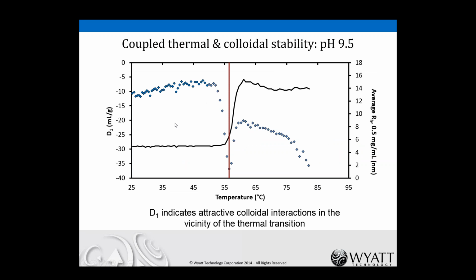So an interesting study that we did here was to look at how D1 changes with temperature around the unfolding transition. And so here's that antibody that I showed you earlier. Here's D1 as a function of temperature. And you can see that until we get to the range where it begins unfolding and aggregating, it's fairly constant with temperature. The black trace here is the average RH. So here again, RH is stable until we get to some transition where it increases from about 5 nanometers to about 15 nanometers. And this region over here would be the onset of aggregation.